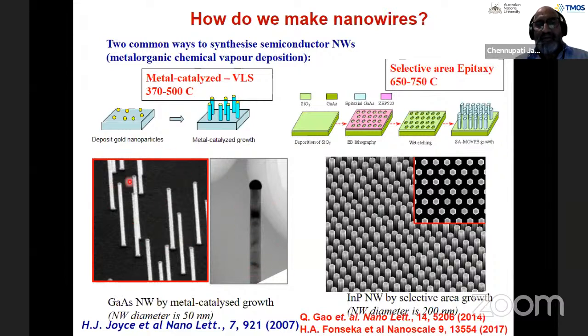This is a scanning electron microscope image of these gallium arsenide nanowires, which are about 50 nanometers in diameter. You can also see the gold nanoparticle sitting on the top and the gallium arsenide nanowire at the bottom here, indicating that we can really control the dimensions of these nanowires by essentially changing the diameter of the nanoparticle which we are using here. This is an example of a 50 nanometer nanoparticle which Hannah Joyce happened to use. Because we're incorporating a vapor into a liquid and getting a solid, Wagner and Ellis at Bell Labs in the 60s called this process the VLS growth process.